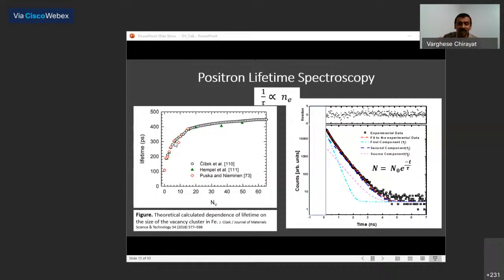Now remember, the strength of positron lies in small defects, right? In mono vacancies and di vacancies, it will give you a very large difference in positron lifetime. Not in vacancies which are extremely large. You have transmission electron microscopy and high resolution transmission electron microscopy to see defects which are greater than a 10 vacancy cluster. You can use TEM for that. But for seeing a single atom vacancy, it is very difficult to do that using transmission electron microscopy, and positron is the best tool available to do that.